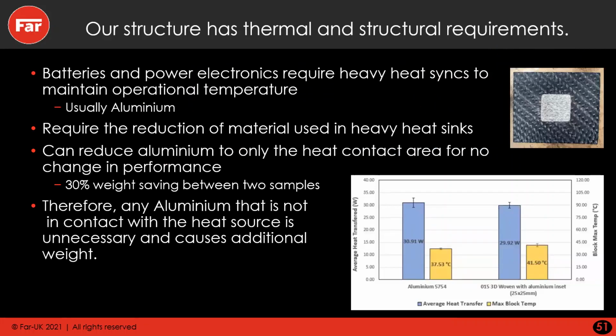So battery cells and power electronics both require thermal management, which usually comes in a form of heavy heat sinks, which are usually aluminium. The bar chart in the bottom right shows a heat transfer of the two different structures. One of the structures is wholly aluminium 5754, and the other is a carbon fiber composite with a 25 by 25 millimeter aluminium block embedded through the thickness. Carbon fiber is a relatively poor conductor of heat compared to aluminium. Aluminium is around 200 watts per meter Kelvin, whereas carbon is around 0.5 watts per meter Kelvin.